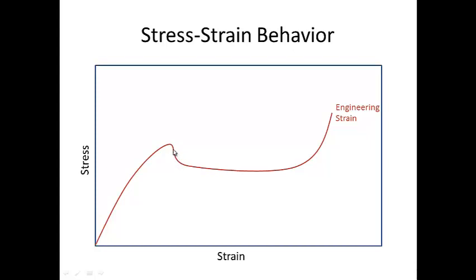Now keep in mind, this is engineering stress and engineering strain, so our assumption here is that the cross-sectional area is being held constant. That's not quite correct. And at this maxima point, we actually have a place where the necking begins, and so the cross-sectional area is changing dramatically. Then we see a region of perfect plasticity, where you get plastic strain without any increase in stress. And then finally, the material work hardens considerably, and you get failure at a very high stress relative to the other stress levels.